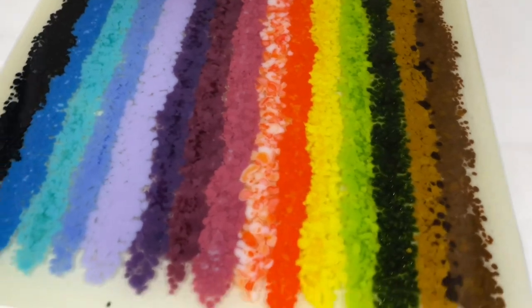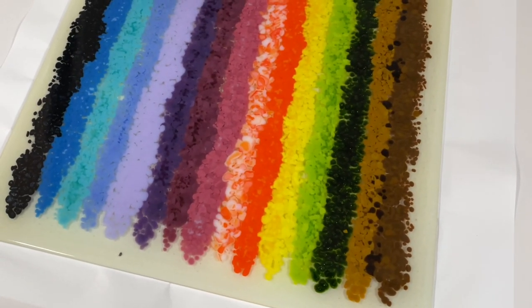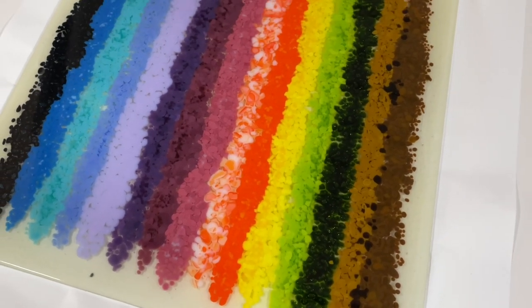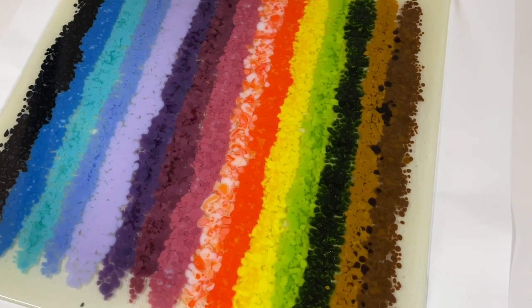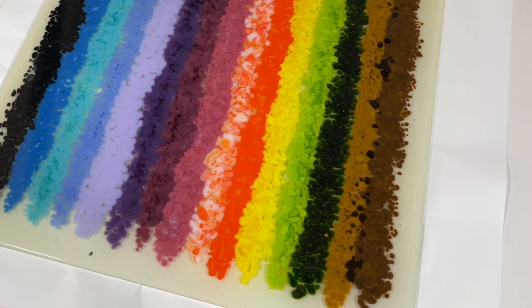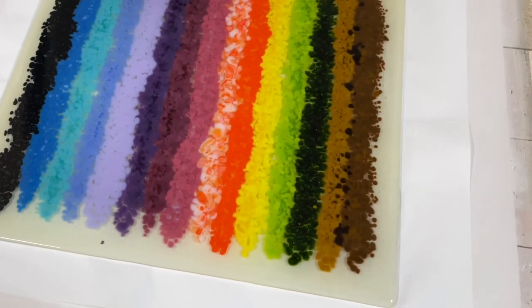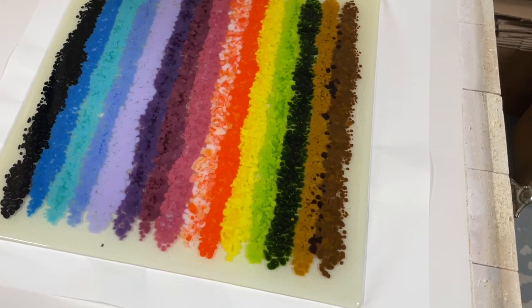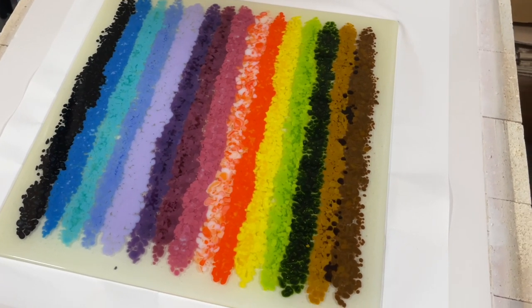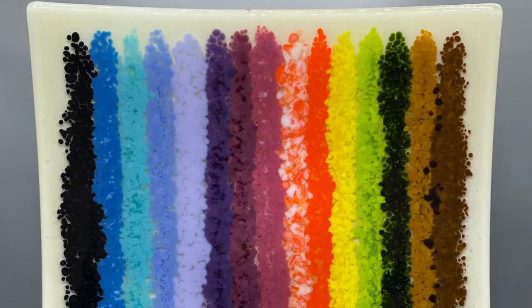It's done — great fuse! I had one piece of frit that jumped off; we'll call it a beauty mark. I'm not sure why frit does that — it tends to move. In this case I didn't use any adhesive whatsoever: no hairspray, no glue, no glass tack — all completely dry frit. I sometimes think those things can gas off or bubble and move frit. Now I'm going to get this cleaned up and we're going to go into a slump. I'm going to use a very slow slump ramp — probably 100 degrees per hour up to about 1150°F — and I'll check the mold instructions.